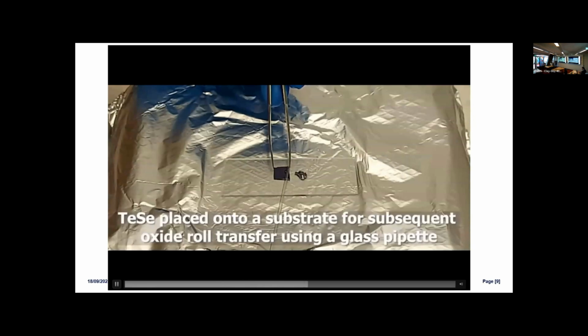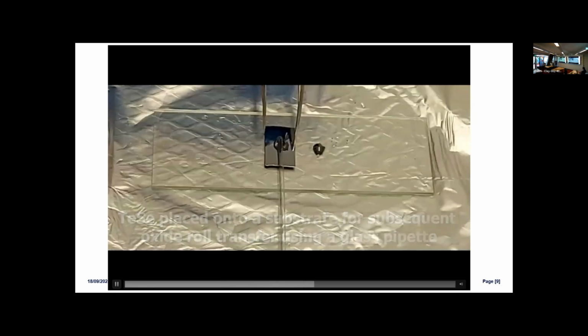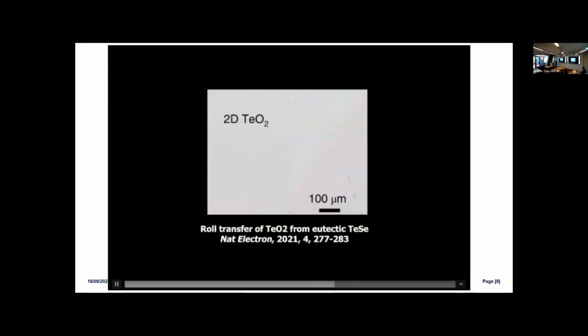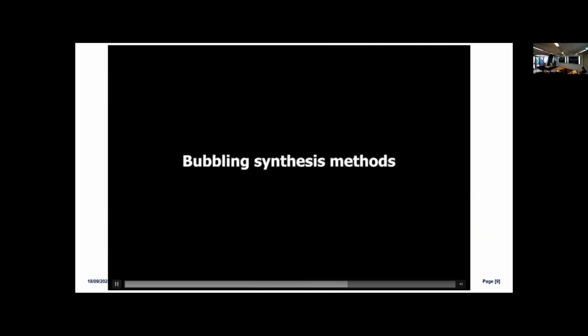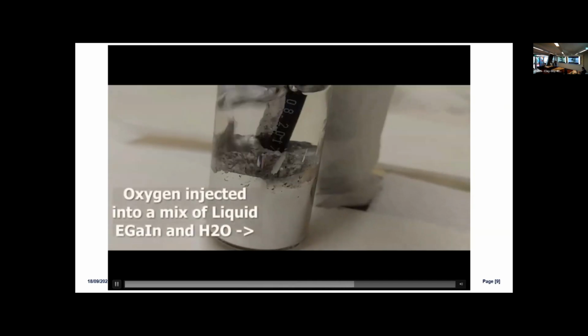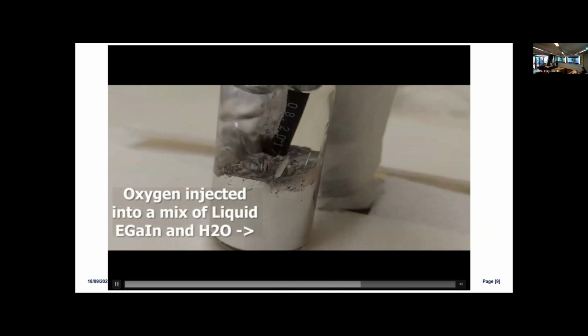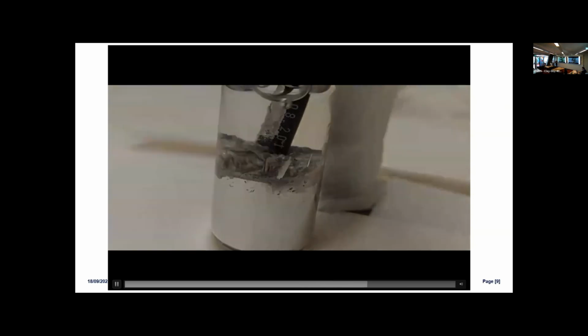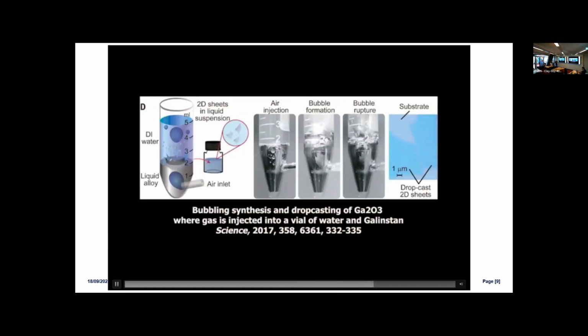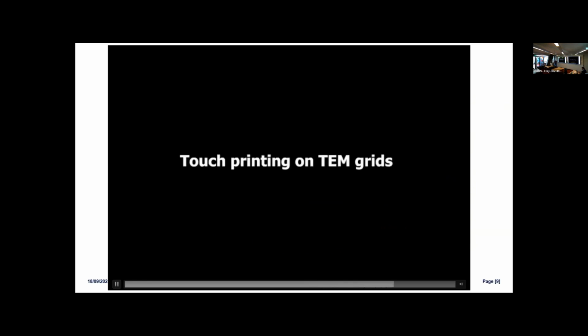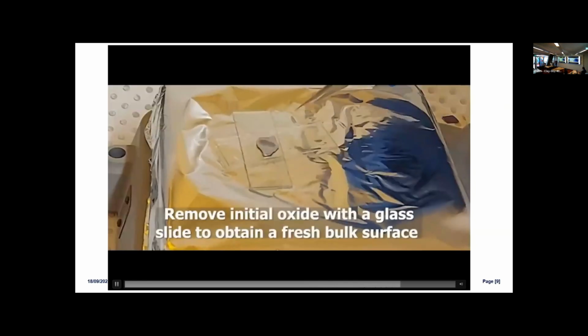The roll printing we invented for this specific mixture because the viscosity was very high, and we had to drag it along the substrate. And also, to get a suspension, we can just bubble any reactive gas. Here, just oxygen-containing gas, and as the bubble rises, it forms 2D oxides and then releases them. Then you can basically drop cast.